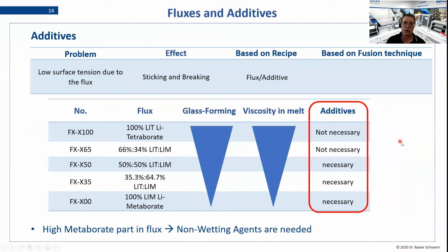So let's move on to additives. Additives like non-wetting agents are used when you are having a low surface tension in the poured melt. So this can be due to the flux. What will this result in? It is sticking and breaking. Like the bead is very flat inside the mold, and at some point it will just break.